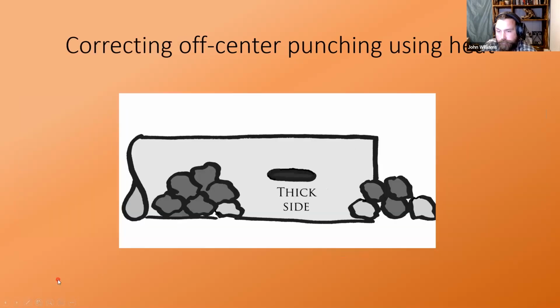You can correct this. This is sort of a cutaway line drawing of how you go about doing this. Assuming that you're working in a coal forge, this would be your solid fuel here. You put the thick side down and a bottom draft, assuming you're on a bottom draft forge. And the bottom draft forge is going to act like a big torch heating from the bottom with the blast going up. So you're going to have more heat on the underside than you will on the top side. So what you're doing is you're using the same sort of principle. You're trying to get the thick side to be able to move. And when you drive your drift through, you want the thin side to stay put, which is the opposite of what happened when you have your punch off center.